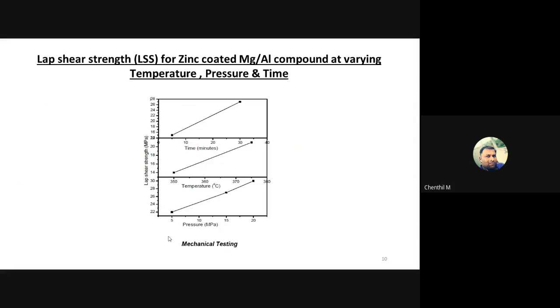So this is the final result which we achieved, this is the lap shear strength for a zinc coated magnesium alloy, compared with respect to temperature, pressure, and time. Here we can see that at 375 degrees Celsius, the lap shear strength was found to be 21 megapascal. So at 375, we have seen 21 megapascal.